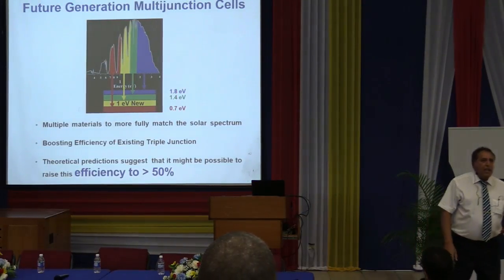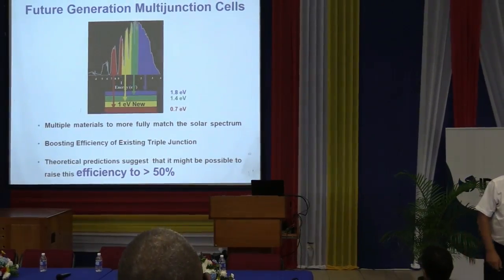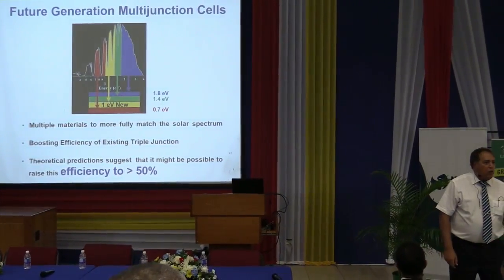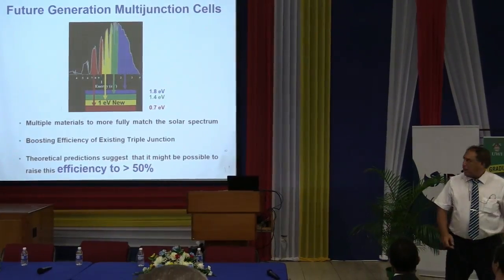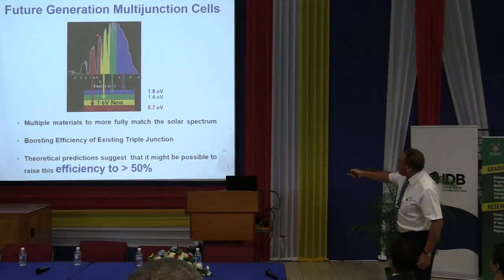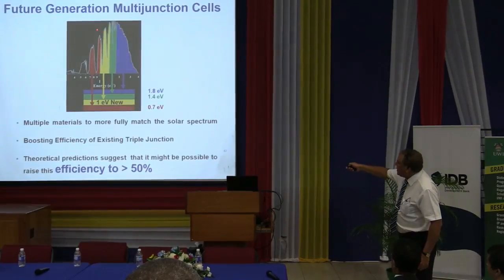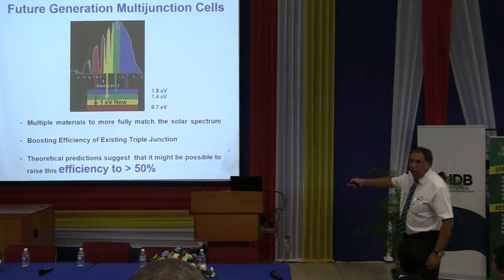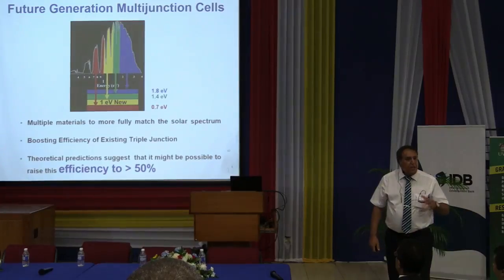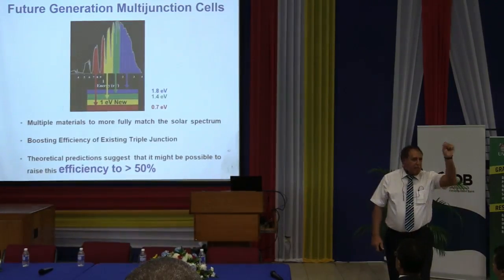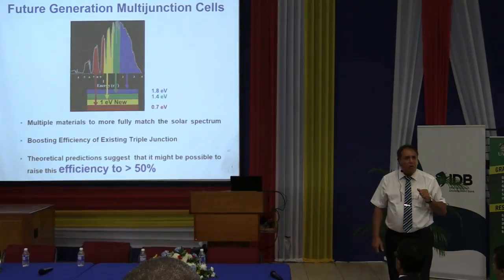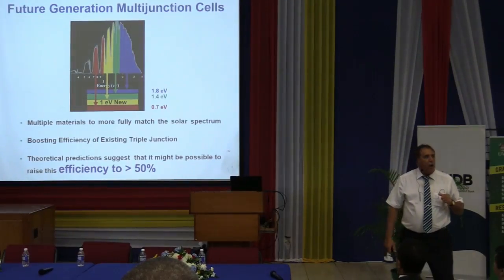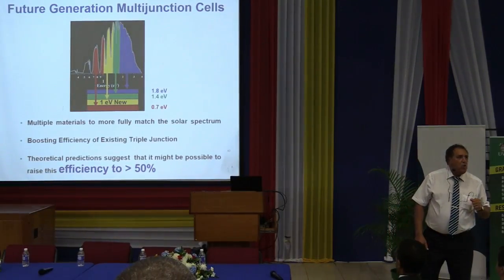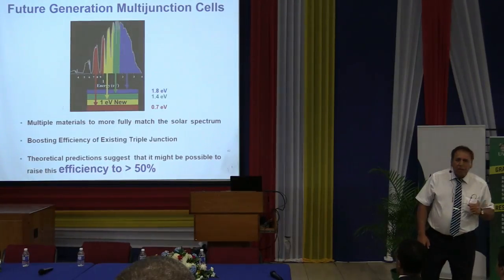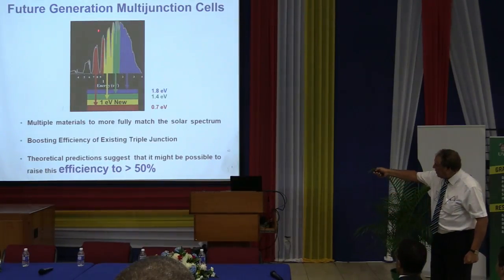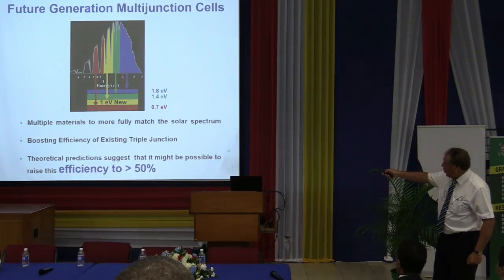So the whole idea is this magic material system called the 1 electron volt material system. If you look at 1 electron volt, this actually is a peak in the solar energy, and that's what you want to capture. Silicon does it very well. That's what it peaks at mainly, because its energy is about 1 electron volt. But for the 3J it was difficult to find a material system which has got 1 electron volt energy. It's a very big challenge, and this is the big energy which you want to absorb as well.